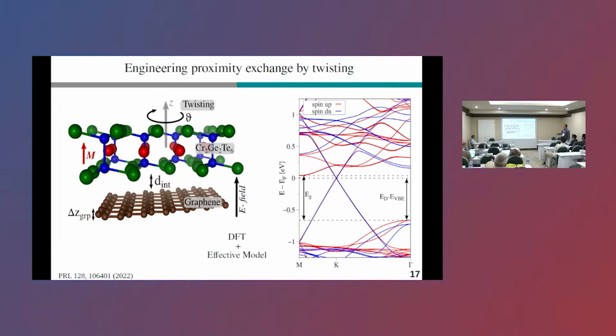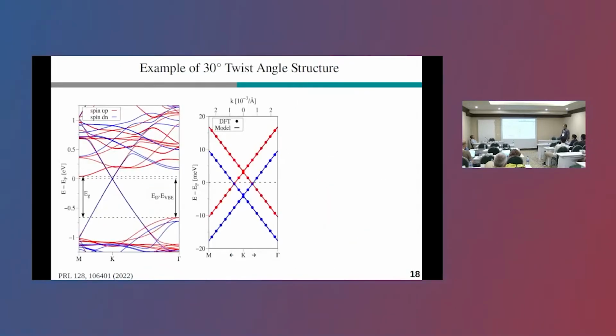And the situation roughly always looks like this. The Dirac states are nicely preserved within the band gap of the CGT. Now let me discuss on a specific example what is going on, which is the 30° twist angle structure. The overall band structure we have already seen. The two different colors correspond to spin up and spin down. And if you then zoom in to the Dirac states for this 30° structure, you will find that the spin down bands are pushed to lower energies compared to spin up.